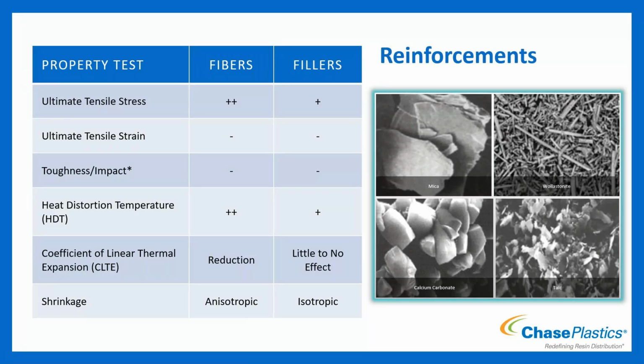With fibers, glass fibers, you're going to see a good increase in your stress or strength of the material. So if it's not quite strong enough, you can achieve that by adding glass fiber. What you will see decrease in, however, is your strain - elongation would be the other term there. So you're going to lose your elongation performance, and typically lose your impact performance.